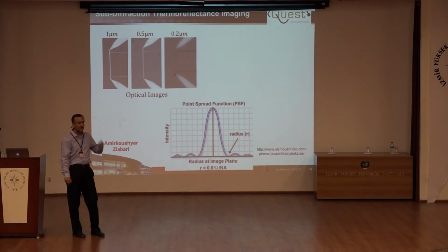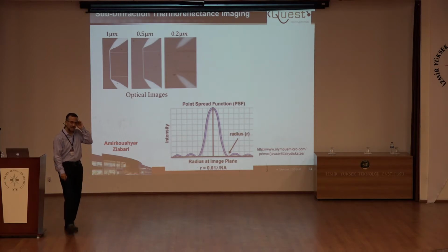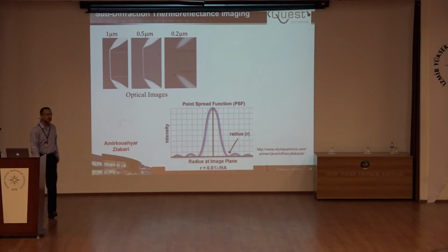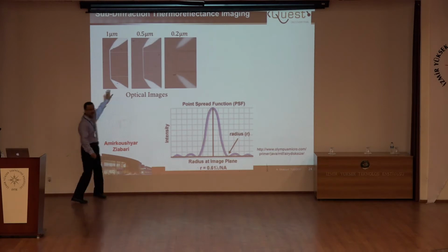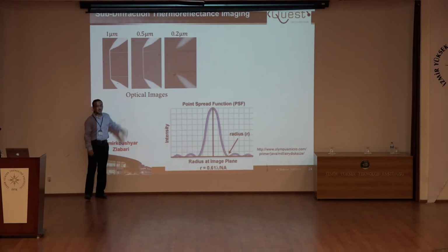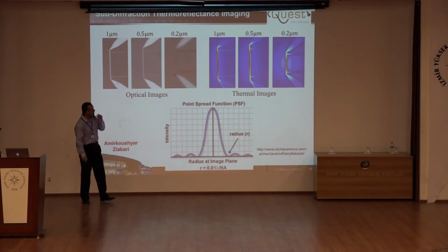What happens when you measure the temperature of the device? As I said, to measure the temperature you take this optical image, you turn the device on and off at 1 frequency, and then you lock into that frequency at each pixel of the image. It should tell you where the hot and the cold spots are.